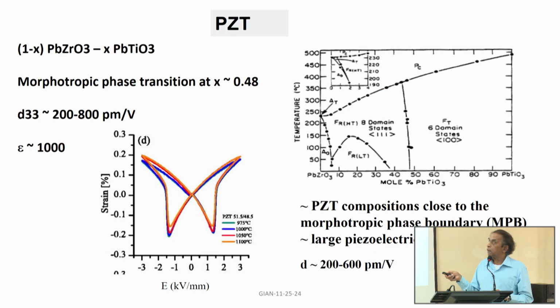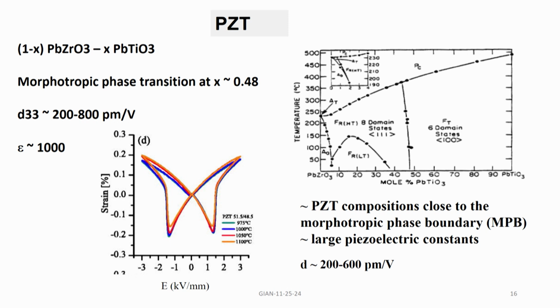PZT is a combination of lead zirconate and lead titanate, and at the morphotropic phase transition corresponding to this composition, it has a very high piezoelectric coefficient, and this is the traditional d33, or strain versus electric field. It starts with 0, goes high, it can be as high as 0.2%. Then as you come back in electric field, the polarization can suddenly switch, and the strain can become from tensile to compressive. That is what it means. Compressive means negative, tensile is positive, so it can be both positive and negative, whereas barium titanate can be only one sense. So, the d value is on the order of 200 to 600 picometers per volt for PZT.